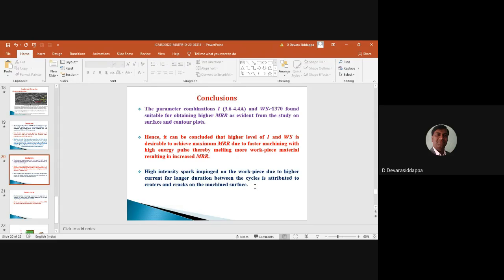In respect of the SEM surface morphology study, we have observed cracks and craters on the machined surface. This is due to high intensity sparks impinging on the workpiece for a larger duration, drawing more current at a higher value of current, which is responsible for craters and cracks on the machined surface. So these are the concluding points from my research work.